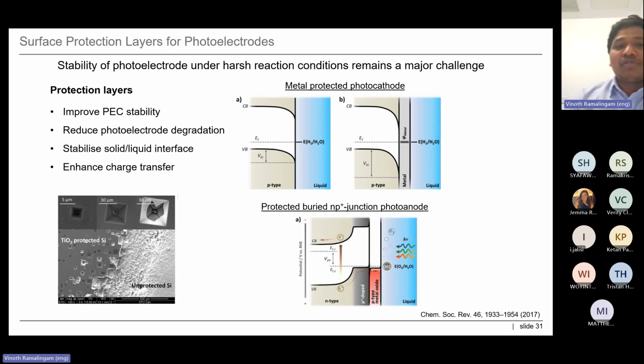Another thing is the surface protection layers. The stability of photoelectrodes under harsh reaction conditions remains a major challenge in PEC. During the photoelectrochemical reaction, the photoelectrodes tend to degrade very quickly. In that case, we need a protection layer. The protection layer is nothing but a very thin layer of metals or metal oxides coated over the surface of the photoelectrode, which can prevent the degradation of the photoelectrode and also enhance the charge carrier separation at the interface, so that we can improve the overall stability of the photoelectrode.